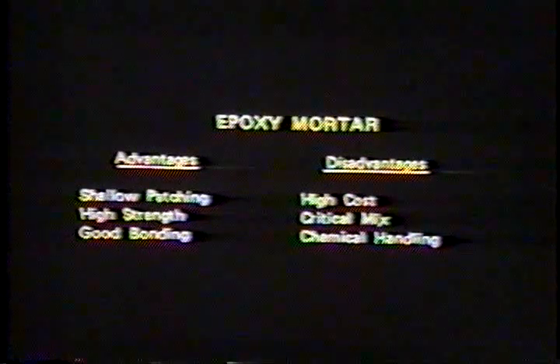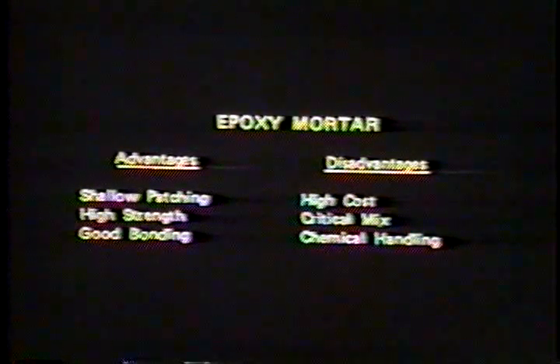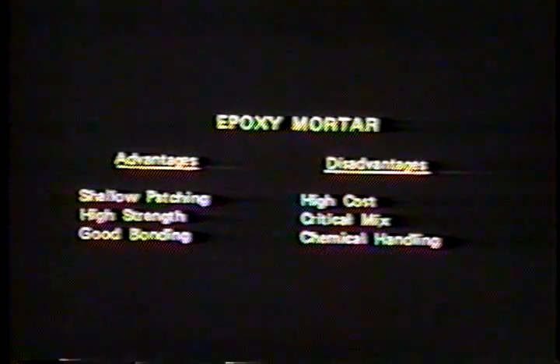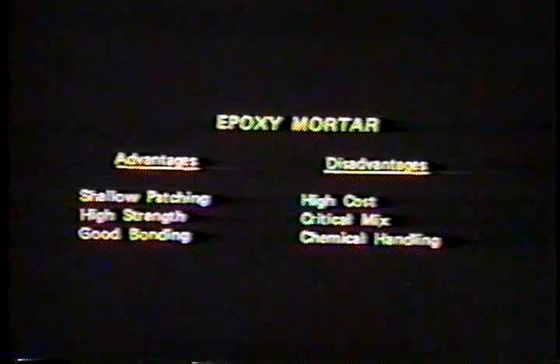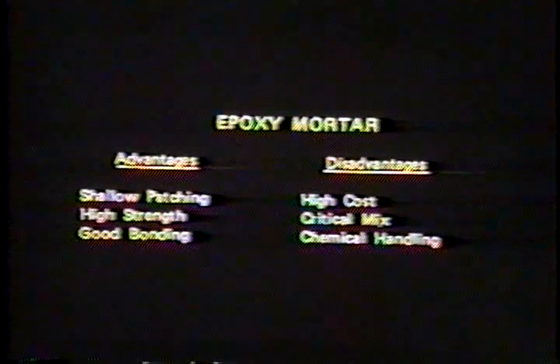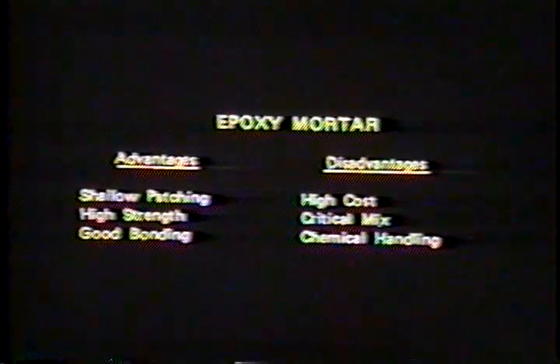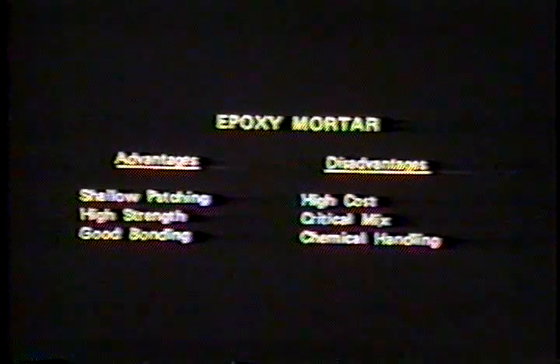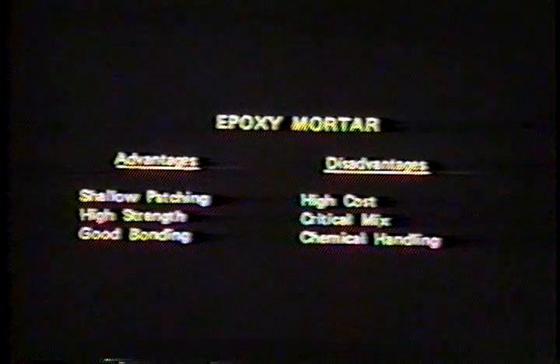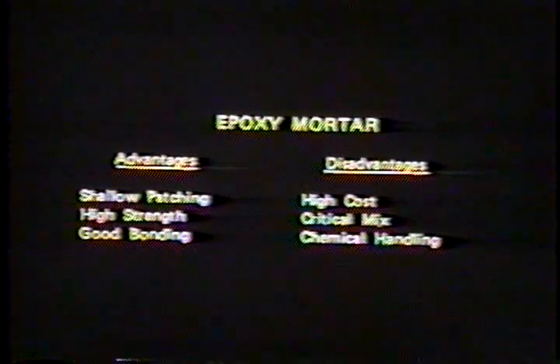Epoxy mortar. Epoxy mortar is the only material that has the strength and bonding to work satisfactorily in shallow patches, those patches 1 inch or less in depth. The cost is very high. Your mix of epoxy and sand must be just right, or either the patch shrinks and cracks if too rich, or is too porous if too lean. Handling the chemicals can be hazardous, and tools must be carefully and quickly cleaned.